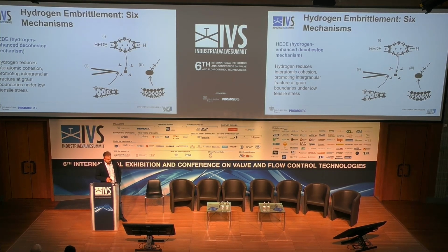Here we don't have any kind of photos because this is still a theory, but it's very similar to what we saw in the first mechanism and in the second mechanism. It's more or less a combination. HEDE is a hydrogen-enhanced decohesion mechanism. So basically, hydrogen penetrates to the lattice of the metal, inserts itself inside the cracks, and once it starts to interact with the metal, it kind of forces the metal to decohese from each other.